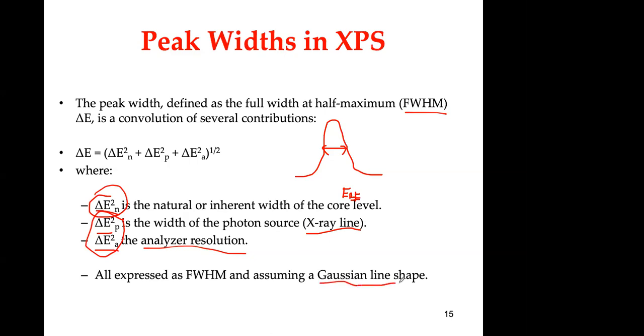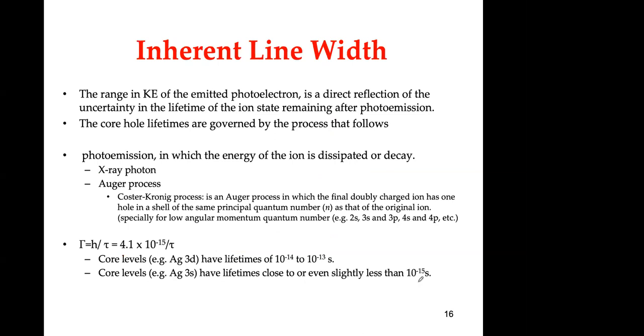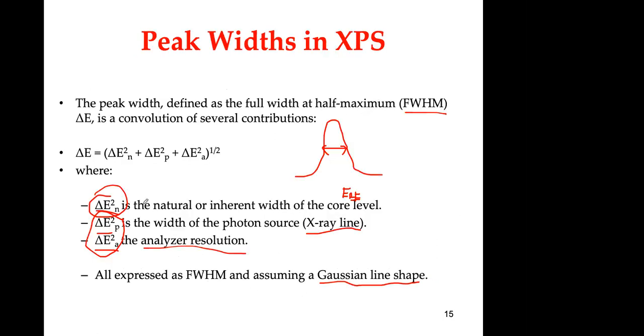Usually the shape is a Gaussian shape, but it also has a Lorentzian factor. But in general, it's usually a Gaussian shape distribution. This is the information of the inherent delta E that I mentioned initially. One of the things that has to be taken into consideration is the lifetime of the hole. After you remove a core level electron, how long it takes affects the delta E. For example, depending on these two core levels, this is for 3S of silver or 3D of silver, the lifetime is different. And having different lifetimes will affect the delta E that I mentioned here, the first delta E, the natural inherent one of the element and level that you are analyzing.